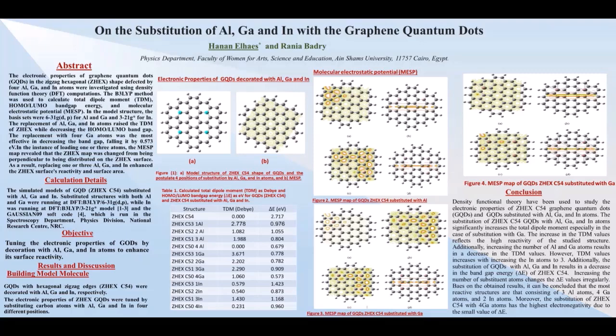Additionally, increasing the number of aluminum and gallium atoms results in an increase in the total dipole moment values. However, the total dipole moment values increase with increasing the indium atoms to 3 dopants. Additionally, the substitution of carbon atoms with aluminum, gallium, and indium results in a decrease in the band gap energy of ZHEX C54. Increasing the number of substitution atoms changes the band gap energy values irregularly.